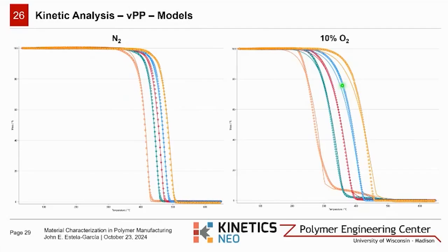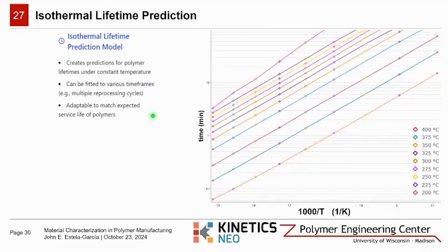And this allows us to predict the material behavior and exposure to these conditions over short and long periods of time. And we'll appreciate that by utilizing the inert results here to construct what are called isothermal lifetime curves. An isothermal lifetime curve, which is shown here on the right, is an excellent, powerful view for understanding polymer behavior under constant temperature conditions. This approach allows us to forecast degradation patterns across various timeframes, from short-term processing to long-term processing.